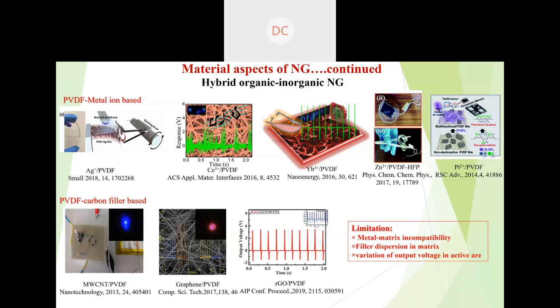Thank you. So recently, researchers have tried to improve polarization of PVDF by incorporation of various fillers, where these fillers interact with the PVDF chains and thus they are oriented in a particular fashion of beta polymer. Among these fillers, there are a lot of metal ion based and carbon filler based, which have limitations in terms of matrix incompatibility and thus filler dispersion in the polymer matrix, which results in low output power, and these also vary with the active area. So next